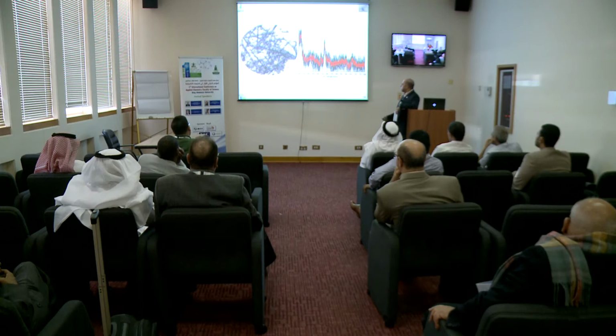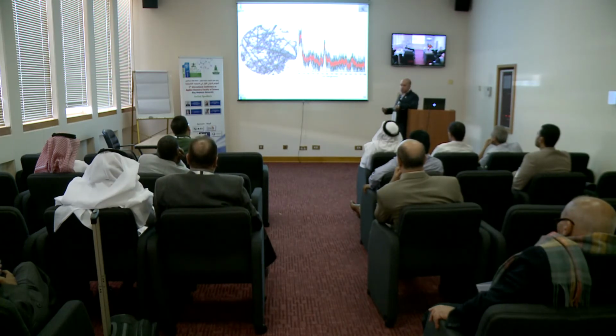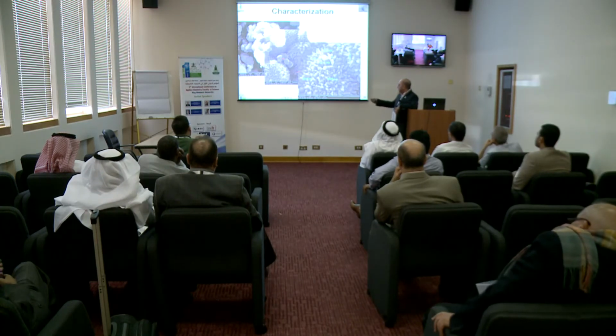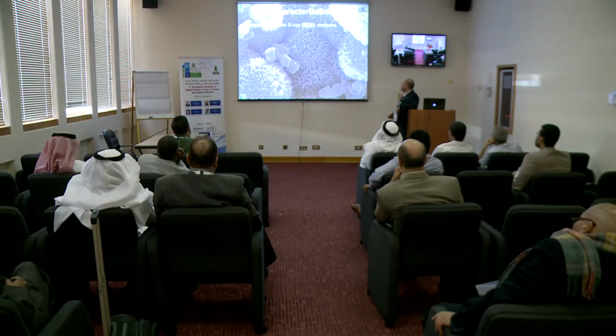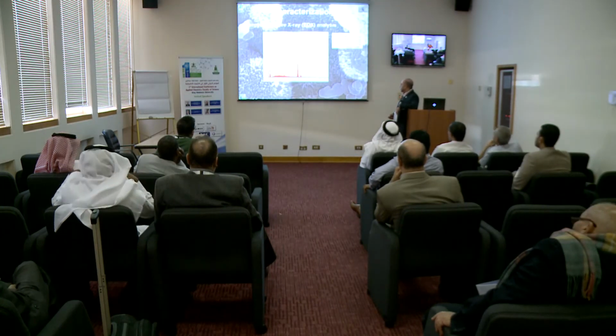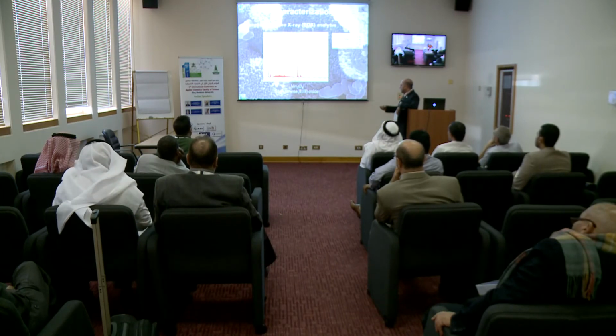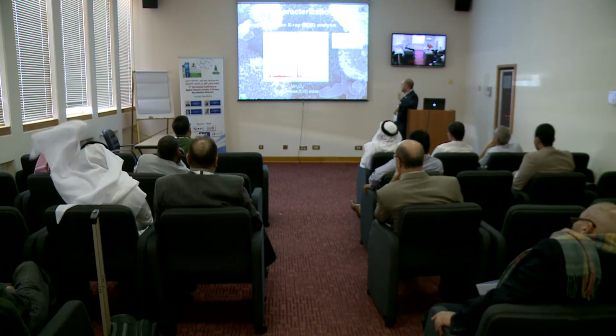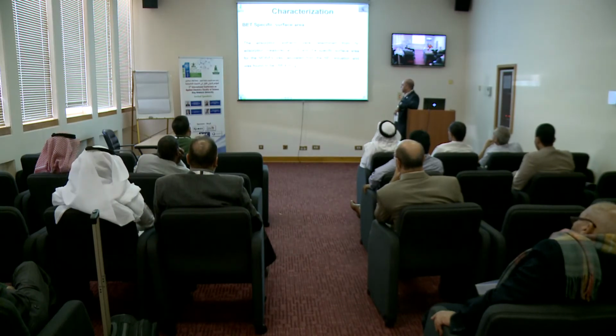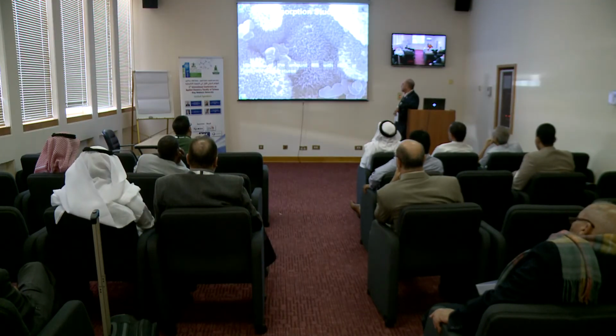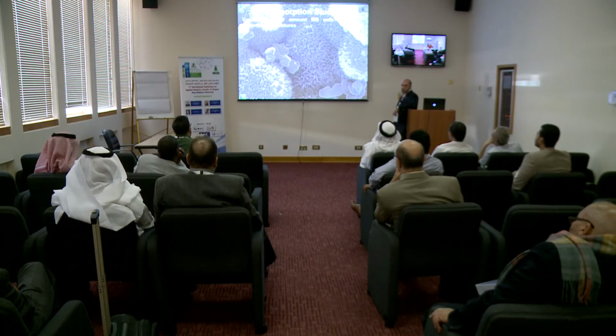We characterized them using XRD to figure out what kind of manganese oxide it is. When we do the TEM, they are in the form of fibers that combine together to look like nanocorals this way. This is the XRD, and it shows this is Mn2O3, a mixed manganese oxide. We measured the surface area, and it is high, around 170 square meters per gram. We use them for an adsorption study to remove methylene blue as an example of organic pollutants from the environment.